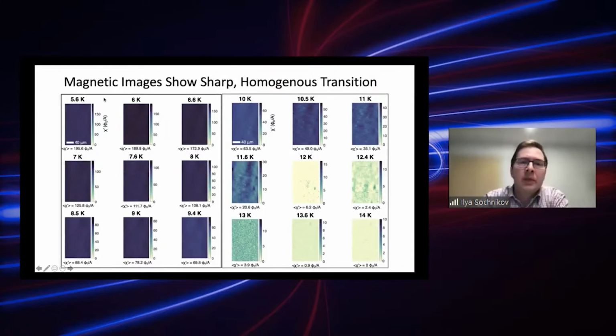So these are typical images taken on one of the overdoped LSCO samples. We start with the lowest temperature, 5.6 Kelvin. You see this blue color, which corresponds to a fair amount of screening. Well, it's basically perfect screening. Then you increase the temperature. This blue color doesn't change much as we change the color scale, but it actually goes down. You proceed, 9.4 Kelvin, 10, 10.5, and then at 11.6 you still see some of the blue color. Then at 12, you pretty much abruptly get a normal state.